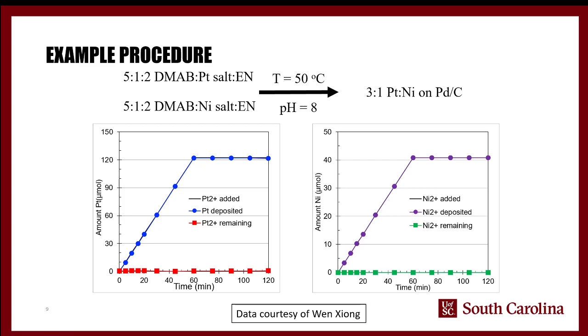and use inductively coupled plasma measurements to find out exactly how much of each of the materials was in the solution. And so what she could show is that based on the complete lack of platinum that could be detected in the solution itself, you know that the platinum must be deposited. And so what she can show is that the platinum deposits readily. And what you can't see here actually is the platinum 2+ being added is trending right along with this line. And so what it means effectively is that we've got 100% deposition. There's no wasted material of either the platinum or the nickel. And that's a really big thing. That really cuts down on the total amount of cost that you have, because you're not having to throw in extra metal just to make sure you get enough to deposit the way you want to.